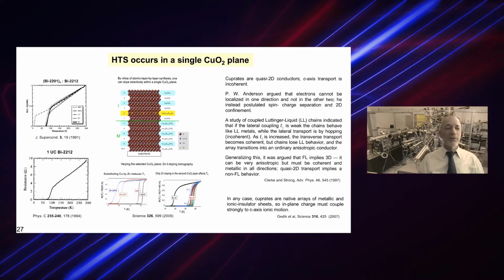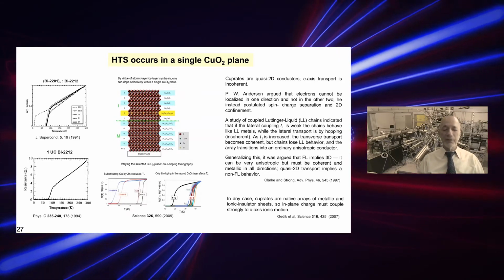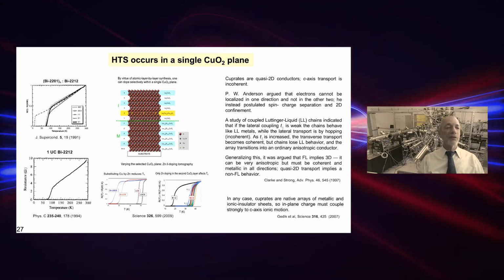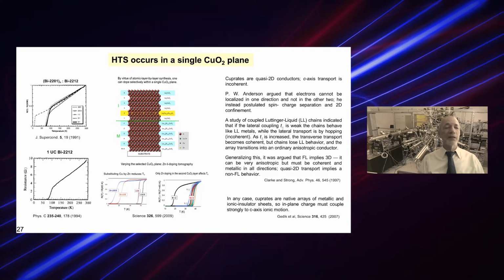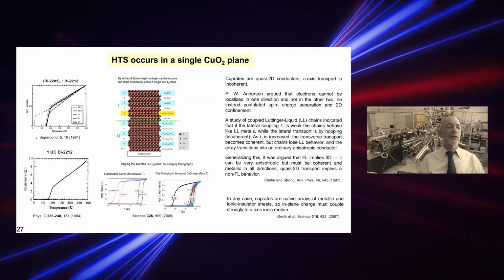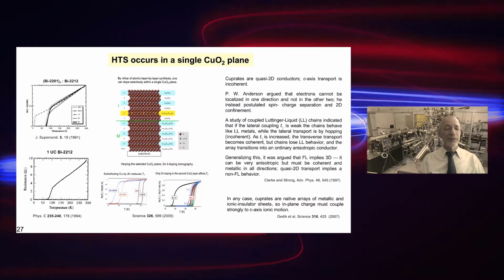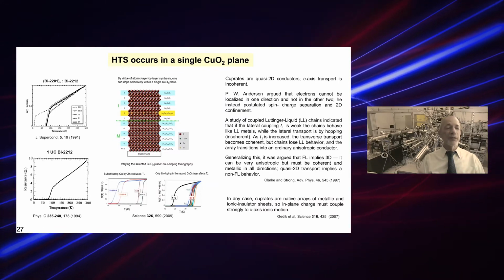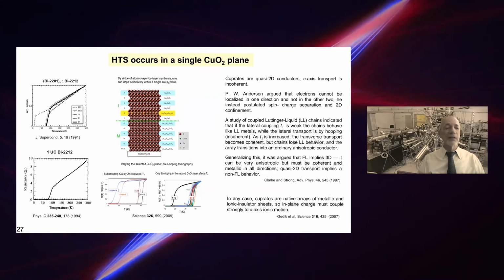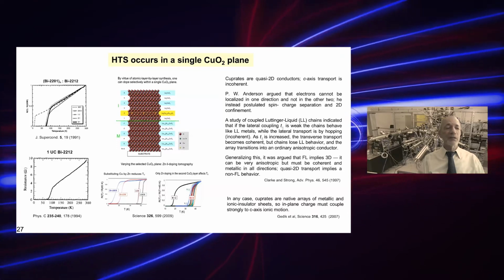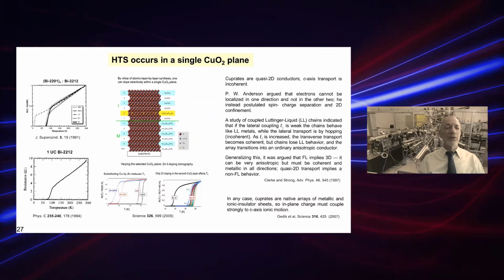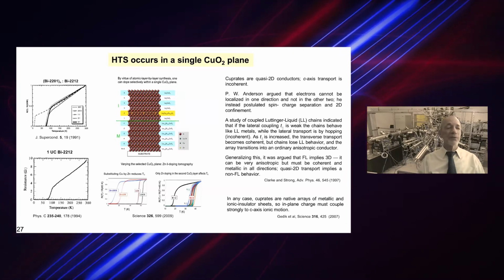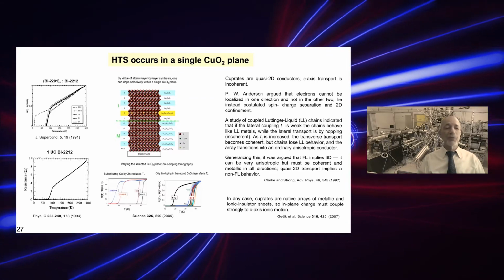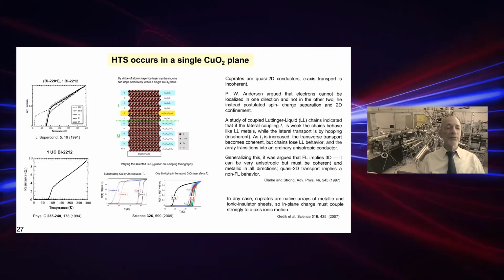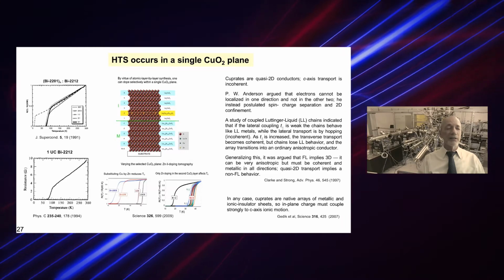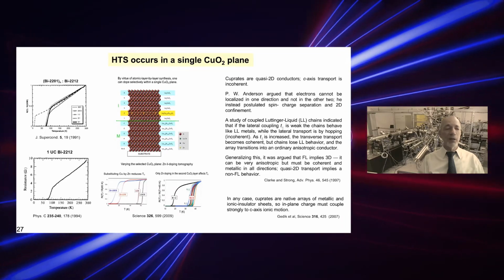Everything that I've said so far was about the metallic in-plane resistivity. The out-of-plane conduction looks incoherent and semiconductor-like. Cuprates are quasi-two-dimensional conductors. Indeed, we have many other proofs for that. The most direct is that superfluid density can be confined to just a single unit cell thick cuprate layer and still have the same TC as the bulk samples of the same material. We have amply demonstrated this over the years. And most recently, a couple of groups succeeded in cleaving BSCCO crystals down to a single unit cell layer thickness and found that TC remained the same as in the bulk.